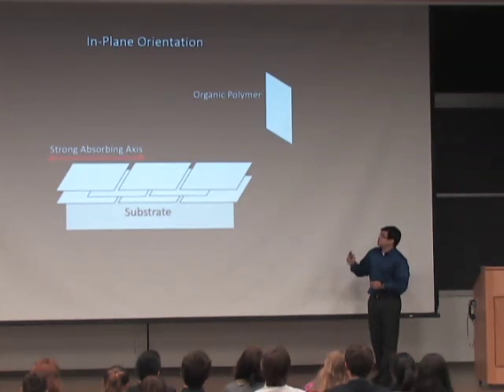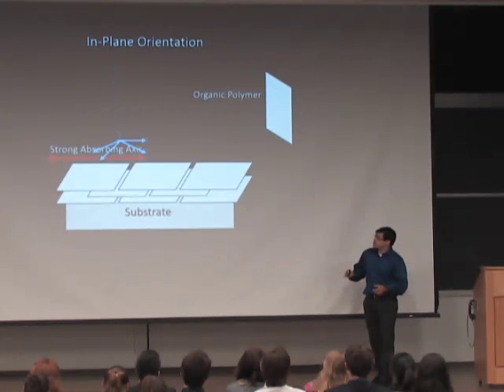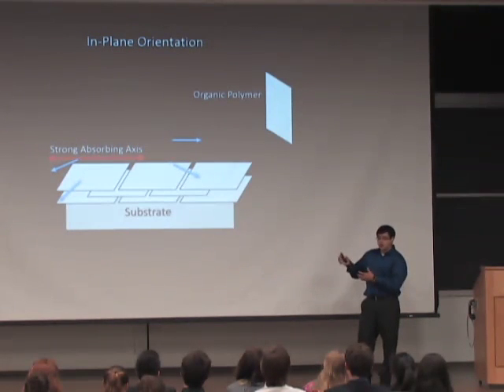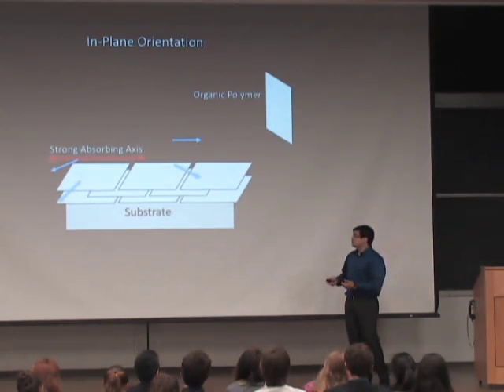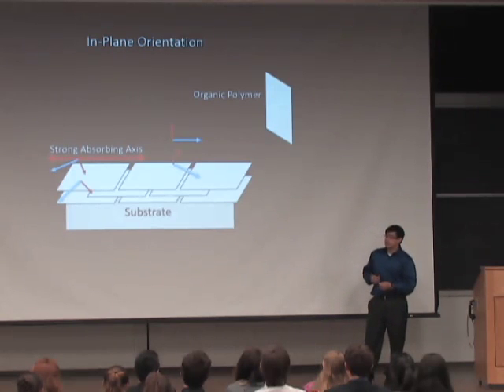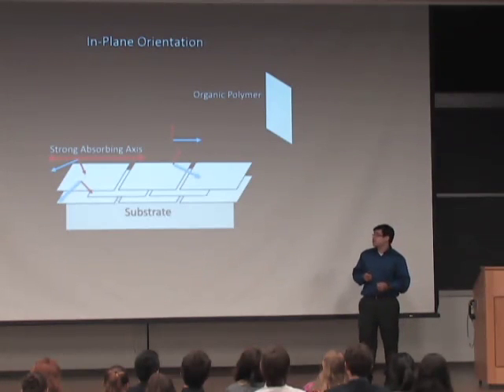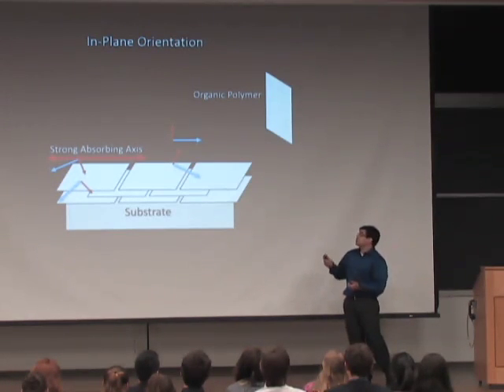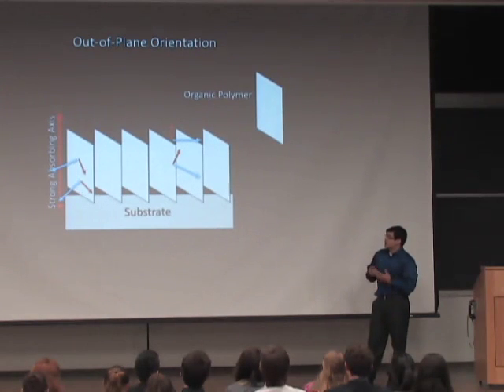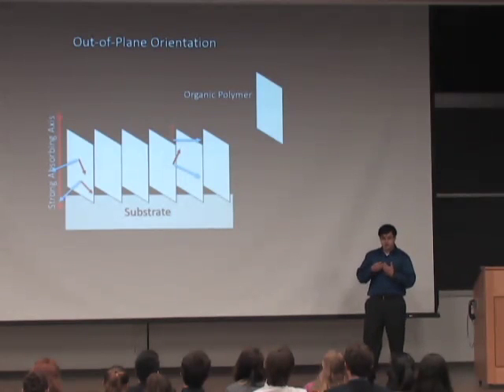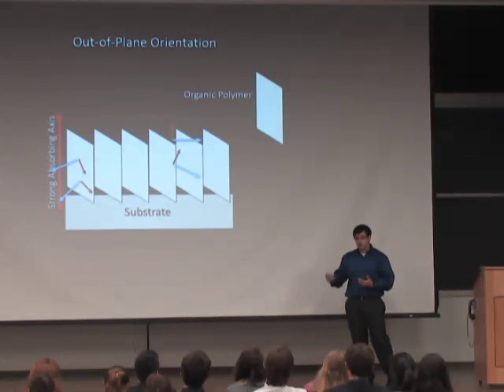And what happens is when light enters the sample, it scatters. And right now it looks like the light is pretty well aligned with the strong absorbing axis. However, when converting light to electricity, we're interested in the electric field of light, which is perpendicular to this direction of travel. And now you can see there's very little correlation between the strong absorbing axis and the electric field. However, there are other orientations, for example, out-of-plane orientation, where now you can see the strong absorbing axis is much more strongly aligned with the electric field, which in the Schuler group we want to show would demonstrate enhanced efficiency.